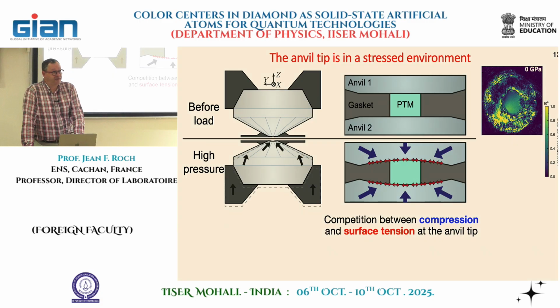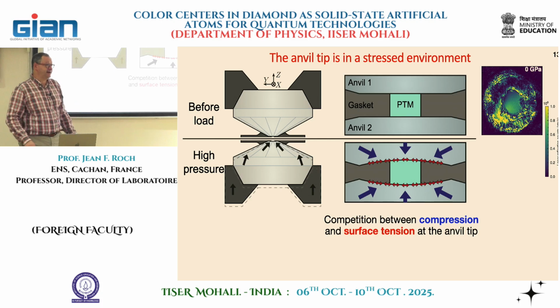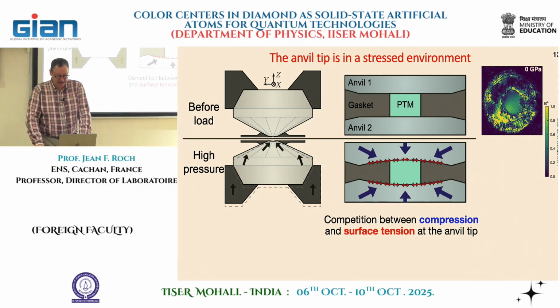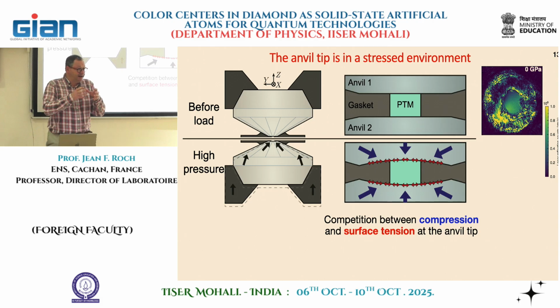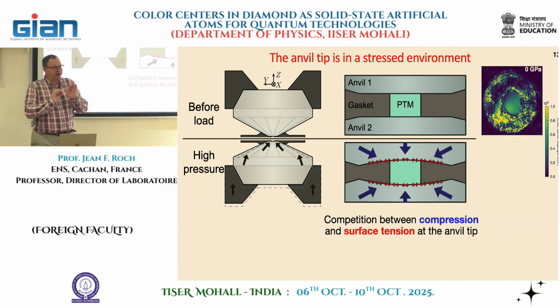If we look more carefully at what happens to the NV in the tip, we have to realize that the NV are in a stressed environment. NV centers are sensitive to many parameters, but they are also very sensitive to the strain or the stress applied around them, in the matrix in which they are located. So, of course, when you build your cell, you have to do very accurate adjustments so that the two anvils are perfectly parallel to each other. If there is any angle mismatch, when we squeeze them, it immediately breaks. So we take great care that the two anvil tips are really parallel.